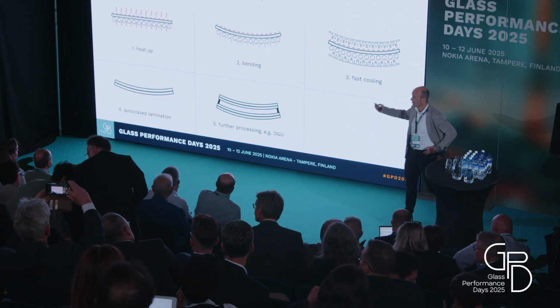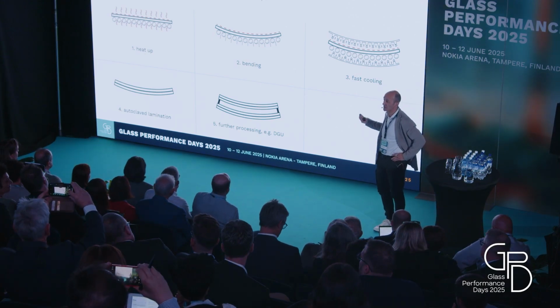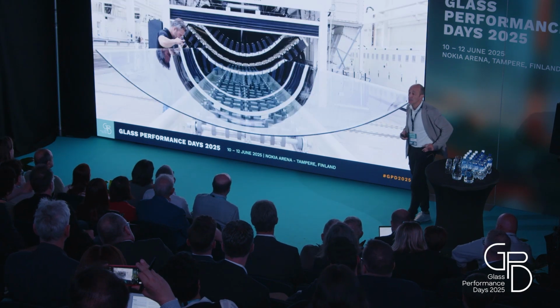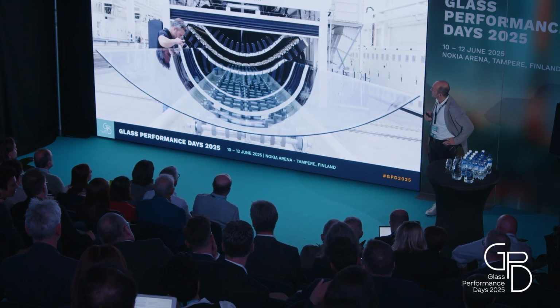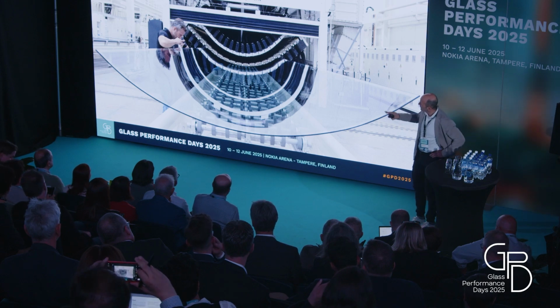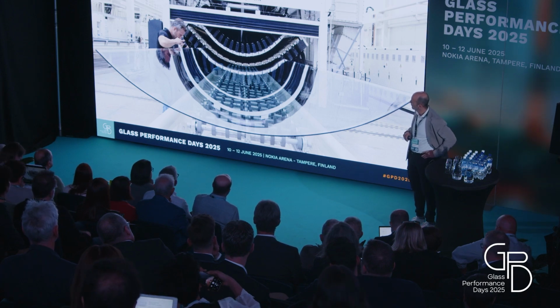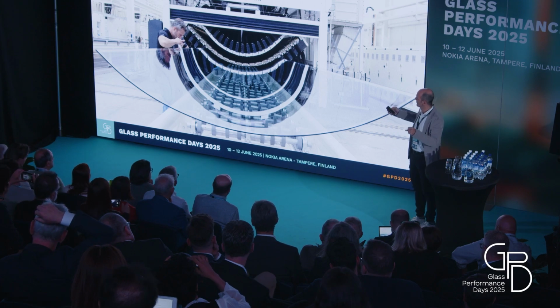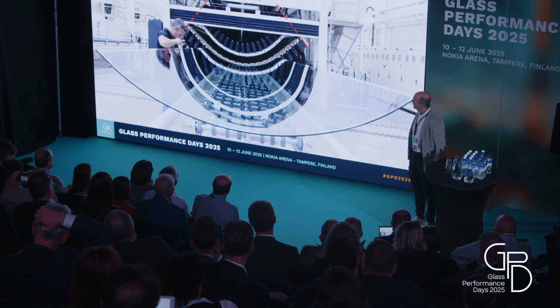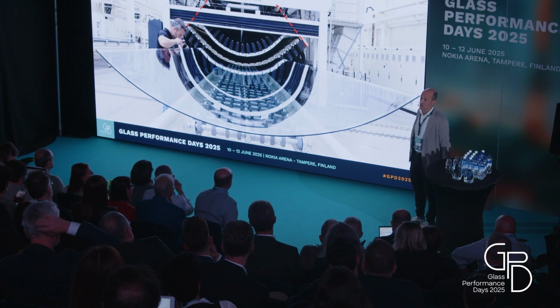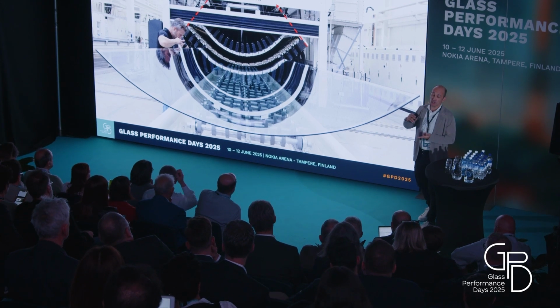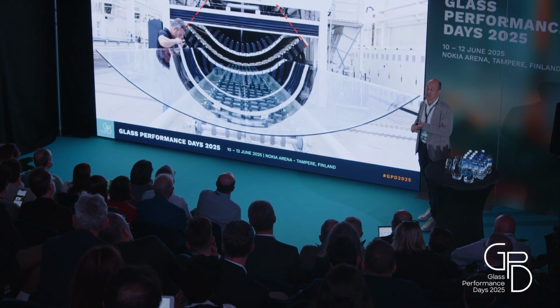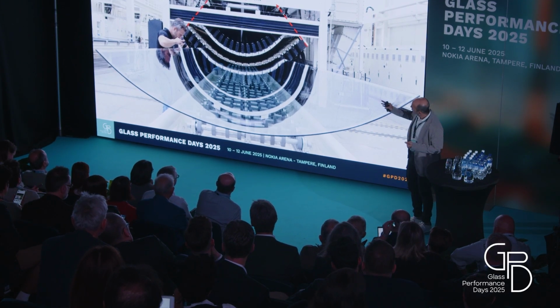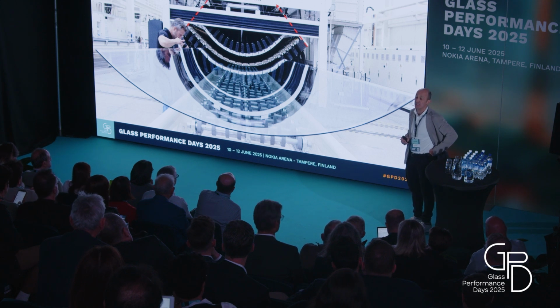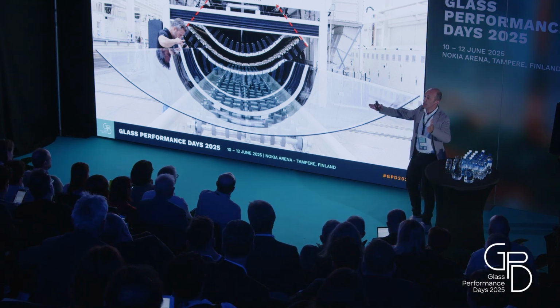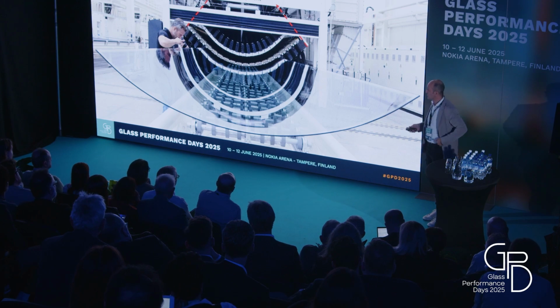Afterwards, logically, we can proceed with any of the configurations, laminating the glass and double glazing. But glass like this is always produced in equipment like this, actually. Equipment where the rollers of the oven basically can be lifted by the sides, lifting up, generating cylindrical, simple geometries. So it's a process that is excellent because it's inexpensive, it's fast, makes the glass strong, but it's limited in geometry. So the central axis at the bottom of the oven is totally fixed. So we can just generate a certain range of radii, but that's all. We are limited to cylindrical geometries.